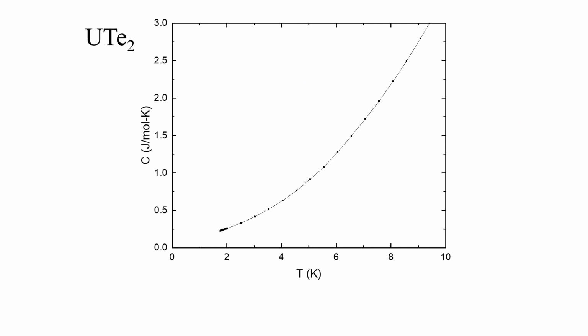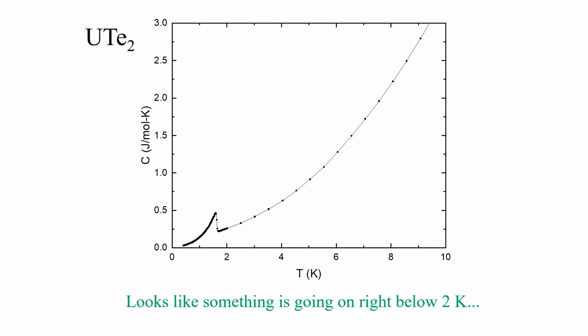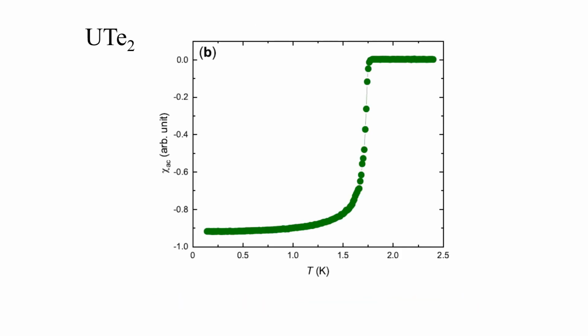So I took the crystal, cooled down, and measured the specific heat. Here is the specific heat data as a function of temperature. Down to 1.8 K, nothing happened, just like what was reported. When I cool down a little bit further, there is an anomaly at 1.6 K indicating a phase transition. Well, what is this phase? I measured the magnetic susceptibility, and this looked like a textbook example of the Meissner effect. The diamagnetism looks like a superconductor.